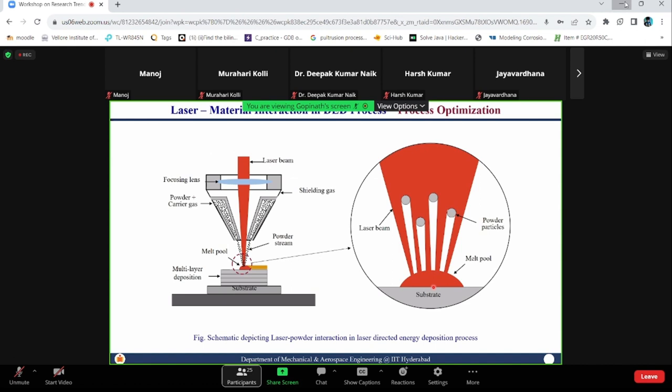Right? Now, let us assume I am using this kind of bead geometry for the overlapping strategy. Then what will happen? Now, if this is my substrate, my bead is like this because of balling. Now, whenever I go for another deposition, you will observe that this zone is what we call the shadowing zone. Means if you are allowing the light from this side to fall onto this bead, this particular location just below this curve will not see any light, right?